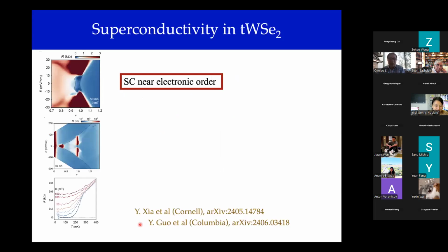So the surprise in recent times, based on measurements of the Cornell group and the Columbia group, is that there's a superconductivity that's sitting near electronic order. So this is this red part of the displacement field, electron filling phase diagram. So it's close to nu equals 1. It represents some degree of electronic order. Maybe there's even localization. And in the extreme vicinity of it, that's where superconductivity is observed, as resistivity versus temperature.